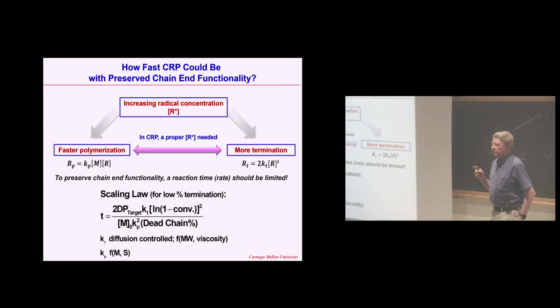So one thing which you need to know is that we would like sometimes to run the reaction fast, but if radical concentration is higher, in that case termination will also be higher, not only propagation. This is a first order reaction with respect to radical concentration. This is a second order reaction. So in principle, you cannot run them very, very fast because you will have too many radicals. They would terminate too quickly, and you need to scale somehow the time of the reaction with conversion, with the ratio of termination to propagation coefficients, targeted degree of polymerization, and the fraction of dead chains you can tolerate, whether it will be 1% or 5% or 10%.